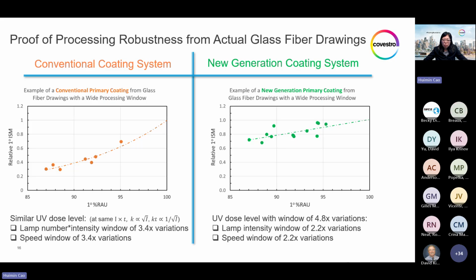So under such a dramatically widened window, the fact that the new generation coating still showed a similar acceptable range of %RAU from 87 to 95% really demonstrates its superior fast cure design. But even more remarkable is the in situ modulus versus %RAU trend. While the conventional coating confirmed following the classic shape of accelerated increase, the modulus buildup, if extrapolating to 100% normalized to 1 for the relative modulus, at 90% of the cure, only reached 40% of the modulus buildup, which agrees very well with our DTS results.